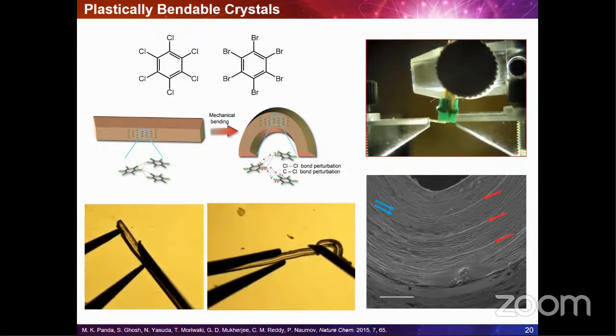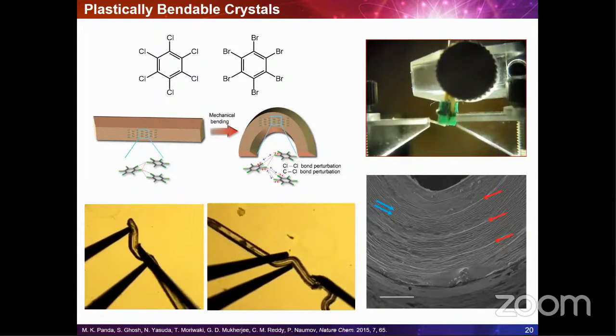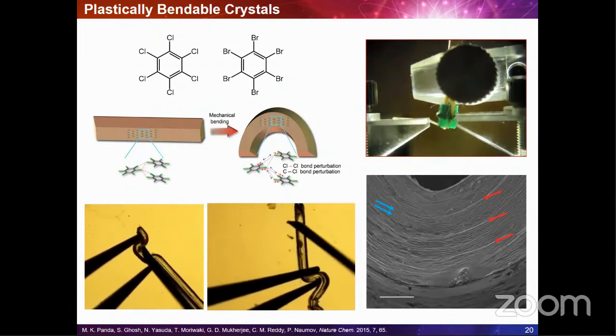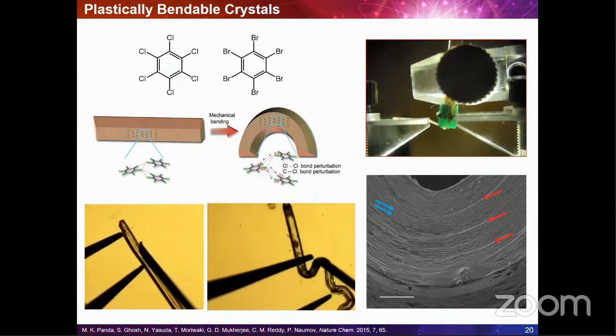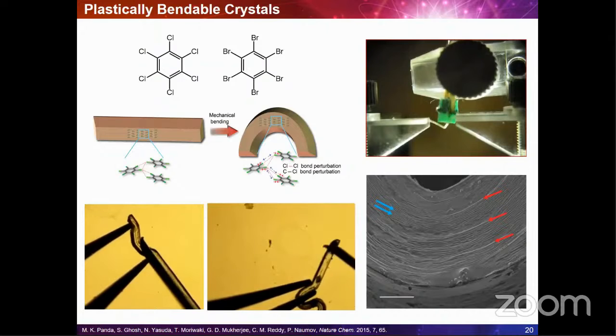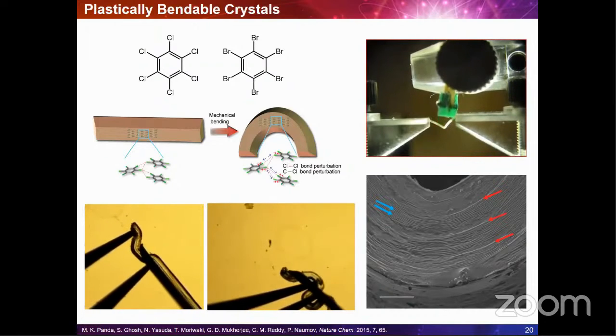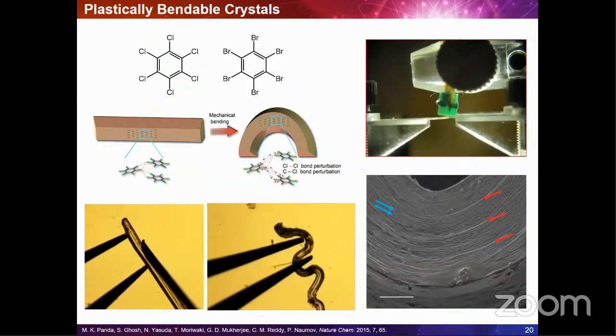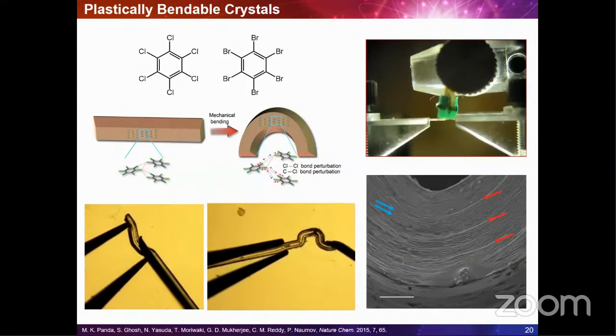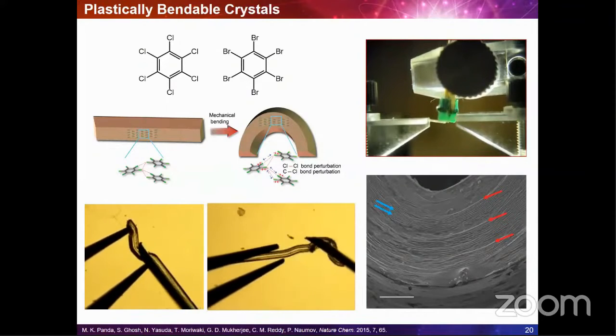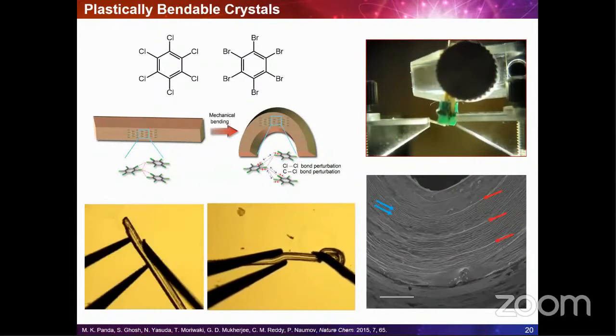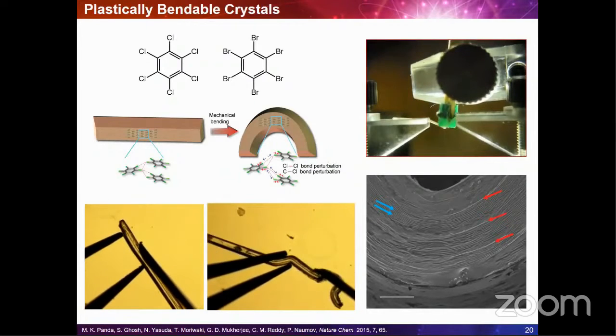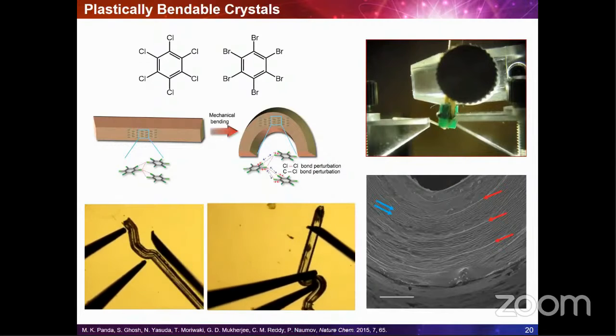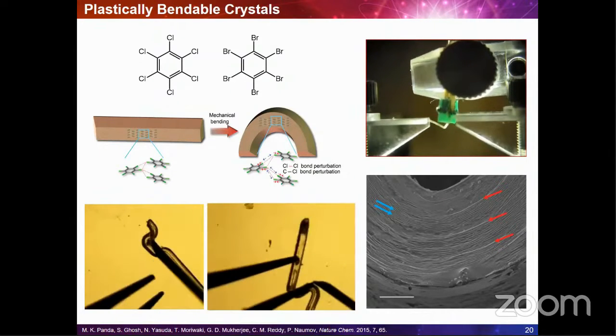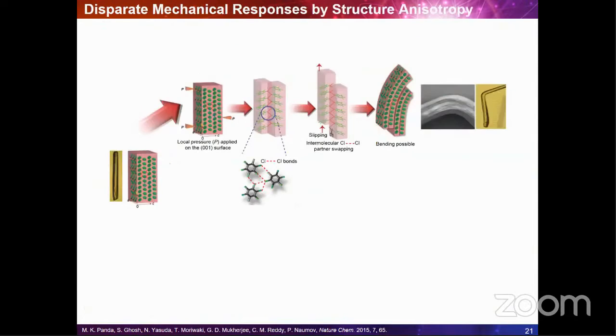In this particular case, you see single crystals of hexachlorobenzene, and there are some other materials as well, which can be bent mechanically at multiple locations to 360 degrees, and they retain their macroscopic integrity. This extraordinary plasticity proceeds by segregation of the bent section into flexible layers. This happens by evolution of dislocations or some defects, and the molecular layers slide on top of each other over these defects, thereby generating domains with slightly different lattice orientations. We have done a lot of different analysis on these plastically bendable crystals, not only of this material, but also a number of other materials.